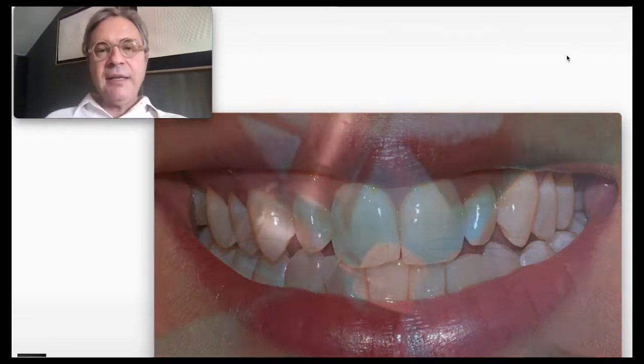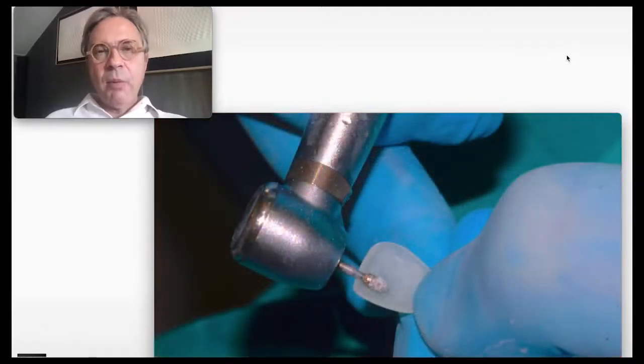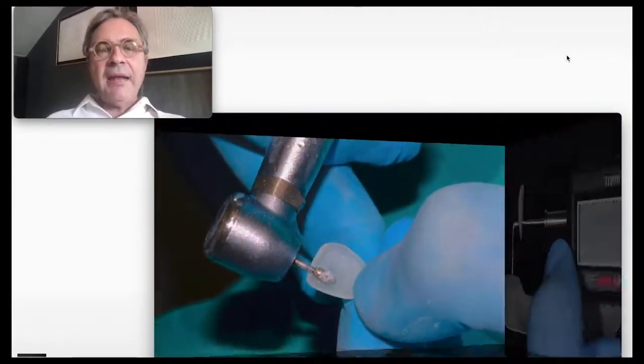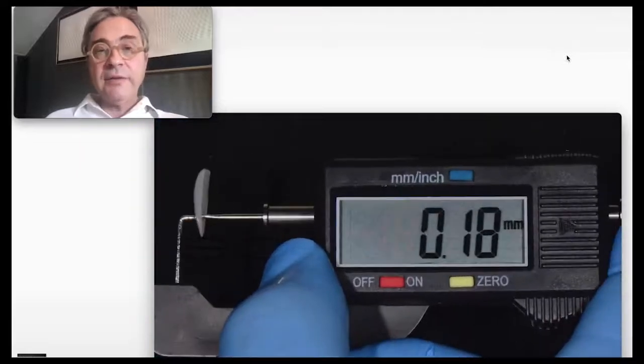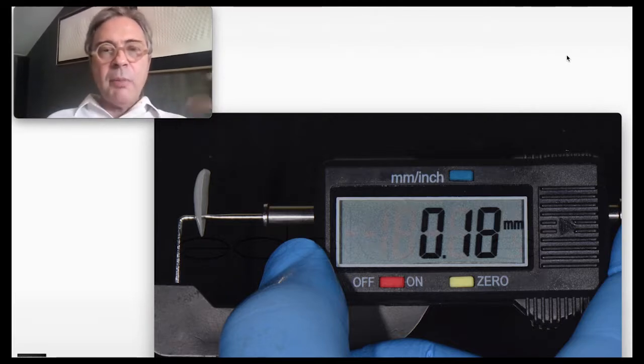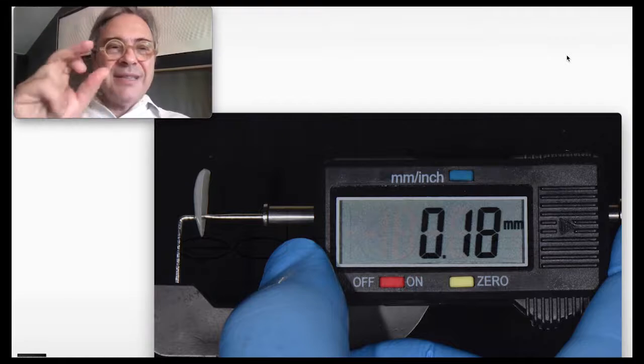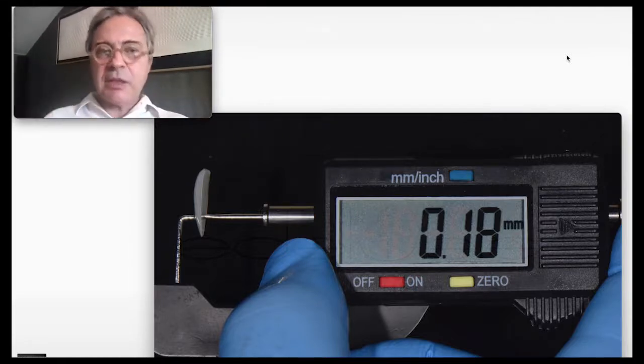And this is what I did for her. I took a diamond burr and I started grinding the veneer inside to make it thinner. And this is how thin the veneer was, 0.18. Now, 0.18 is less than 2/10 of a millimeter. This is super thin. And the good thing with a veneer so thin is that you don't need to prepare the tooth. You can bond it with no tooth preparation because it really adds no extra thickness to the tooth.